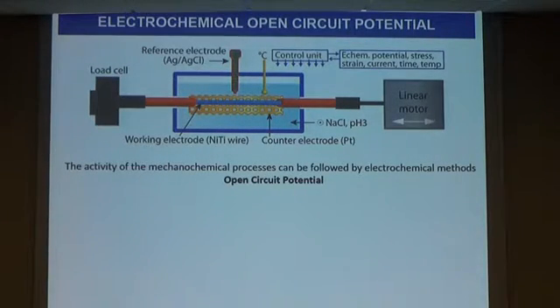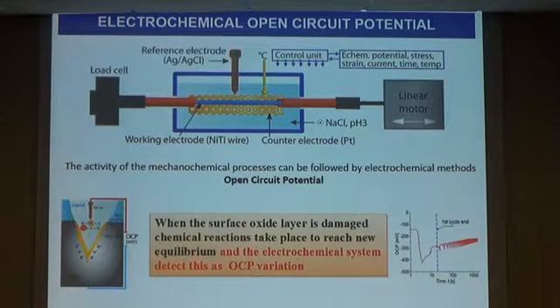And to know how, you have to have some experimental method which sees these processes at the level of oxide cracks, where the oxide could be 10 nanometers. And this method is electrochemistry. If you cycle the wire with a machine and put it into the electrolytic cell and you measure the open circuit potential, you get the information on what's happening on the surface of the material. And so if you continuously record this potential, which is the result of the chemical reactions, you see some drop at the beginning and then periodic cycling until the fracture.